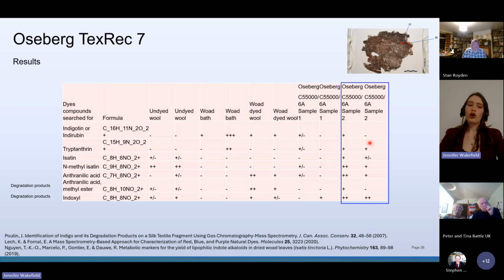And we were also able to look at breakdown products and determine whether or not these masses were present. And what we found is in that second sample that was taken, the one that was more brown, we did find all these different peaks. So because we're searching for multiple compounds, we have more assurance that it is indeed from the woad rather than just looking at one compound.